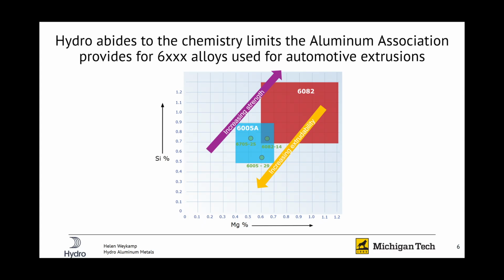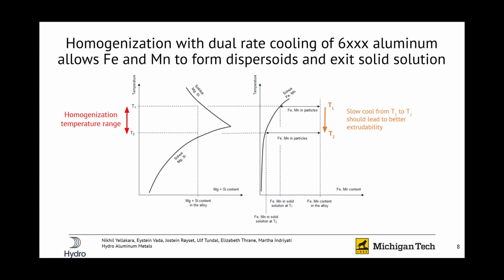Which means if we're trying to optimize the extrudability of these alloys for UACJ, there are 2 things that we can alter, either the composition or the homogenization of these alloys. UACJ would like to keep the same composition because they would like to see the same level of mechanical performance from these alloys, which means that we are looking at altering the homogenization. Homogenization is a thermal process that occurs between billet casting and extrusion to try and create a uniform microstructure for